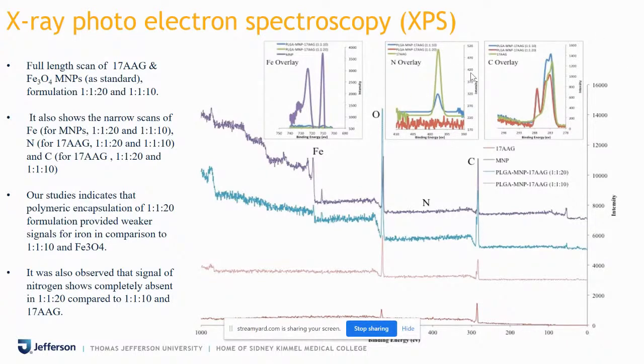Whereas in the case of nitrogen, you see the green color is coming from the 17 AG, which you can hardly see at around 400 binding energy, electron volts. You can see over here, the green signal is coming from the nitrogen. The signal is slightly poorer in the case of 1:1:10, but it is almost not visible in the case of 1:1:20. So we thought that this could be because of the polymeric shell, which is increased by 2 times. Because the polymer cover is so thick, it's very difficult to detect the nitrogen from the surface of the nanoparticles. So then what do we do?